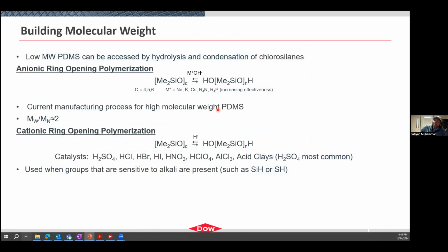Just a quick note about how we build molecular weight. When we first opened up, we talked about the process of hydrolyzing chlorosilanes and condensing them in order to form polymers. Well, that's how we make our low molecular weight PDMS material. But if you want to get even higher molecular weight materials, then we often use ring opening polymerizations. So these are catalyzed reactions where you take those cyclic materials and you open them up and begin joining them together so that you can get larger and larger molecular weights.